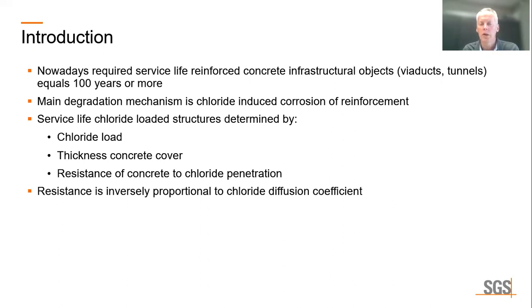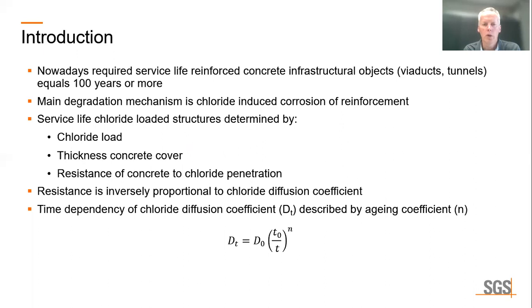This resistance is inversely proportional to the chloride diffusion coefficient. The chloride diffusion coefficient is time-dependent, and the time dependency is described by the so-called aging coefficient N. Here we show this in this equation, where D0 is the diffusion coefficient at the reference time T0, which is usually 28 days. T is of course time, and N is the aging coefficient.